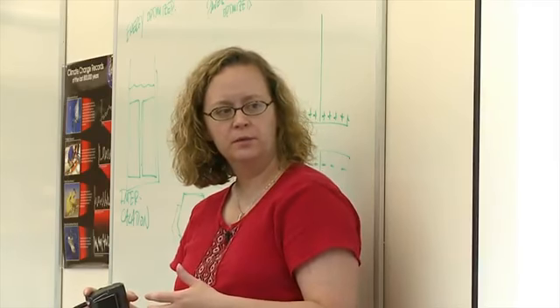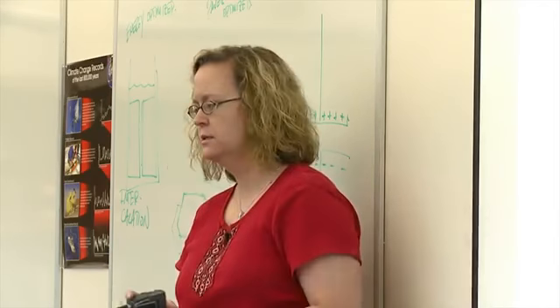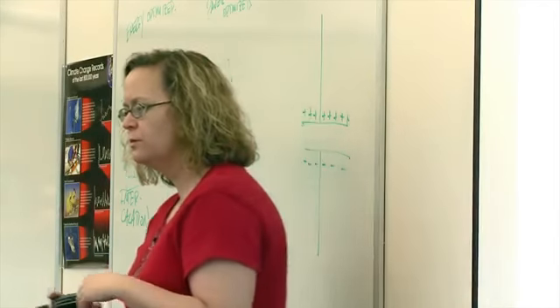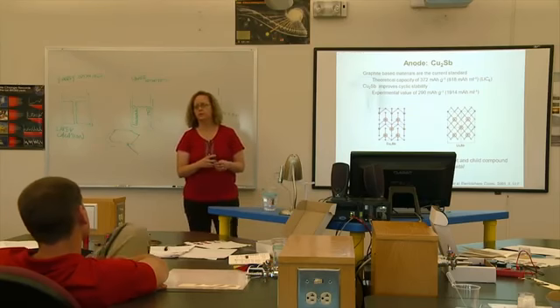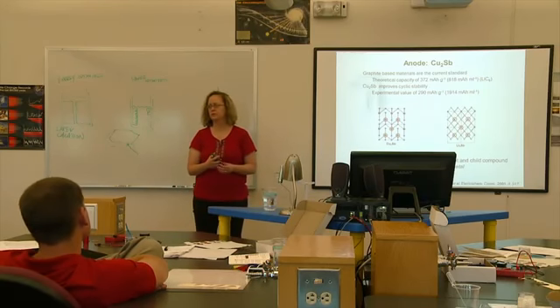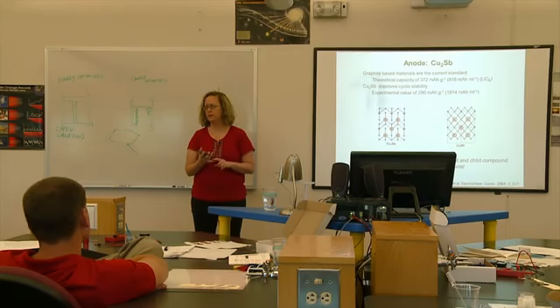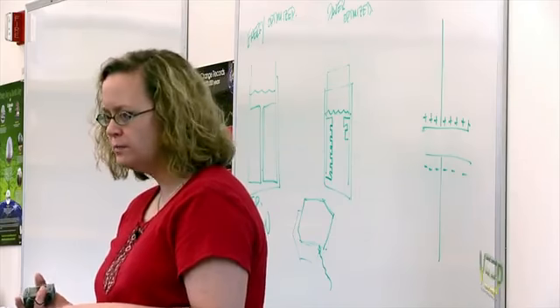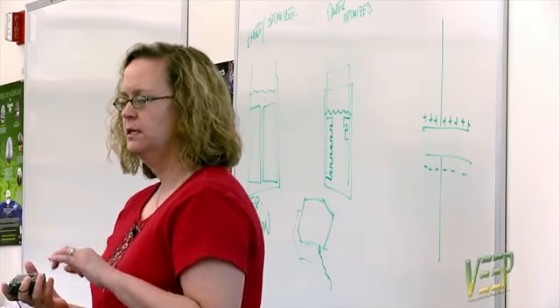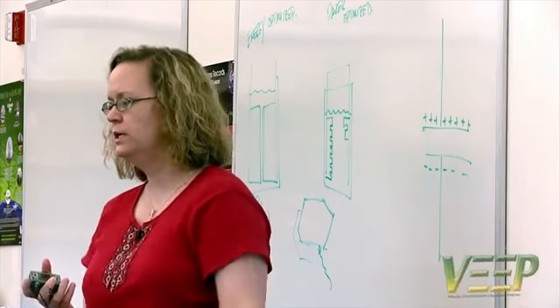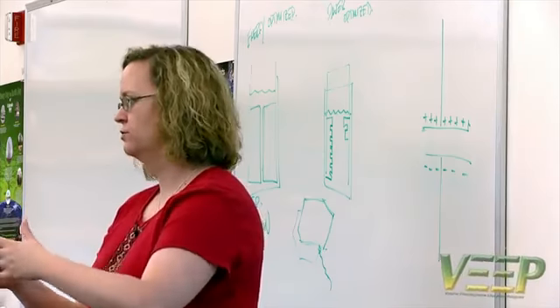What's really important is that it lithiates about 50 millivolts more positive than the plating of lithium metal. So did you guys talk at all this morning about lithium fires or shorting? Anytime you see in the news a recall on batteries, like the big Sony recall, or fires like the FedEx plane that went down because of the lithium-ion battery pack, that's almost always because of lithium metal causing a short. So we can't have that in our battery because everything's too close.